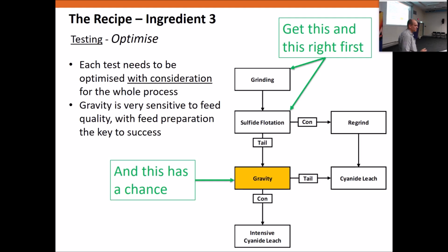So the influence of good feed preparation on gravity success becomes very apparent in ingredient 3 testing. For example, if a preceding flotation step is required to get rid of all your competing sulfides, the following gravity step will just fail if the flotation step hasn't done its job properly. So each test is about getting the result that allows the whole process to work. And I would strongly suggest that gravity is particularly sensitive to feed quality. For example, if you're doing a rougher flotation test and you didn't quite achieve the mineral liberation you're after, the poorer quality composites can still be recovered. But if you're doing a gravity test, they'll end up in tailings or at best middlings.